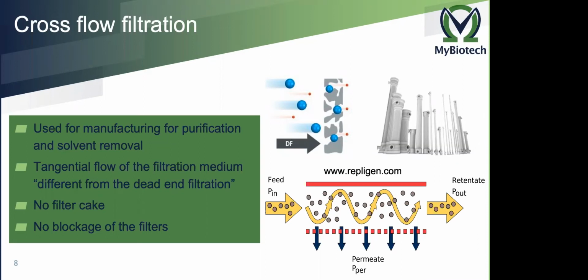Another good thing is that it is a tangential flow filtration, which means the flow is tangential to the filter. So it is not going against the filter like in dead-end filtration, because if it goes against the filter, the nanoparticles get into the pores of the filters, block them, and then you have a problem. Since it doesn't go against the filter, you don't have any filter cake and you don't have any blockage of the filters. You can use the same filter for several dissolution studies.